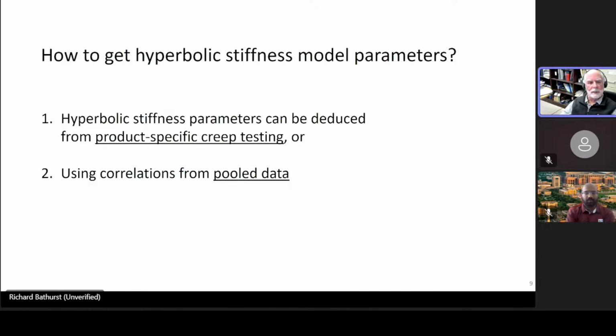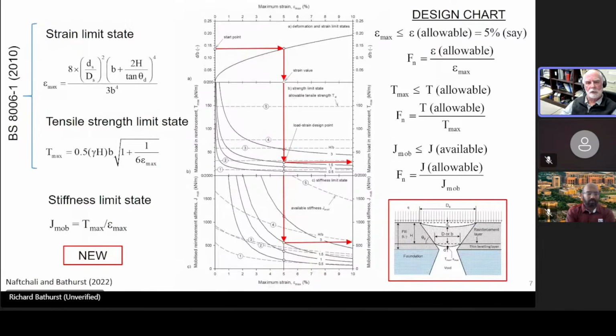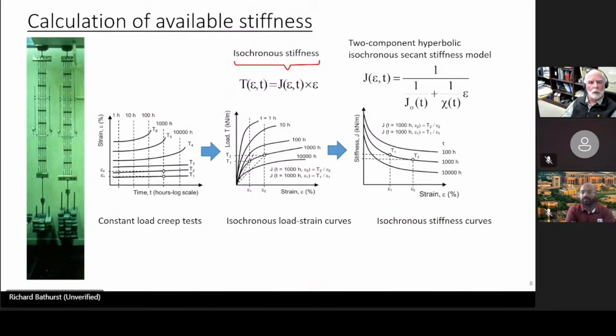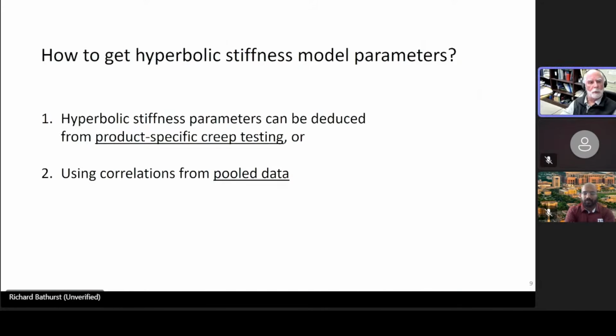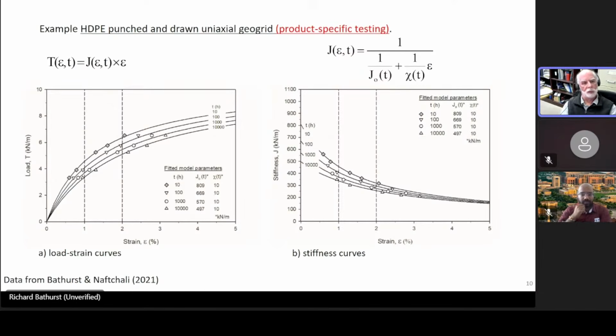So how do we get those parameters in that hyperbolic model, these J and psi terms? Well, we can get these models from product-specific creep testing, or we can get them from correlations that we have developed that I'm going to show you later. So, for example, for a specific product, in this case, a uniaxial HDPE geogrid, you can see the isochronous load strain curves that we developed from these constant load creep tests, and then you see the stiffness curves. And there's also in the legend, you can see the magnitude of those two parameters, J naught and psi, in this figure as well. So you can do this for any product.